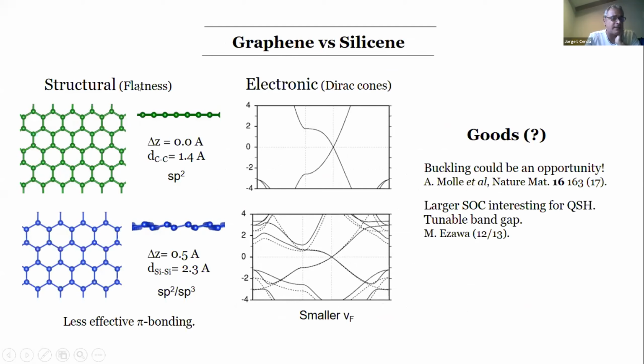Structurally, the main difference is flatness. Graphene is flat, it has no buckling, and the distance between carbon atoms is quite short, 1.4 angstroms, so everything is well sp2 hybridized. When you move to silicene, what you find is that naturally freestanding silicene, from DFT calculations, shows a buckling of 0.5 angstroms, which is not negligible at all, it's quite large. And also the distance between the silicon atoms is quite large, 2.3 angstroms, much larger than in graphene. So basically what we have is a system of mixed sp2, sp3